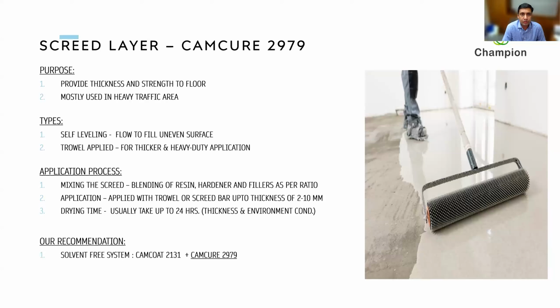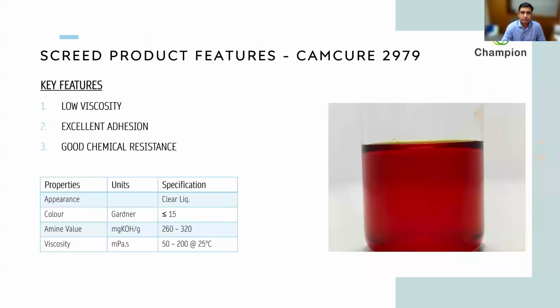Our recommendation for the screed is a low viscosity resin, which is Camcoat 2131. But more importantly, it's the curing agent, which is CamCure 2979, and I'll talk more in detail about the properties. As you can see here, CamCure 2979 is a pretty dark colored product. It's reddish brown in color, but it has a very low viscosity. It gives excellent adhesion both to the primer as well as to the top coat, and also provides good chemical resistance properties.